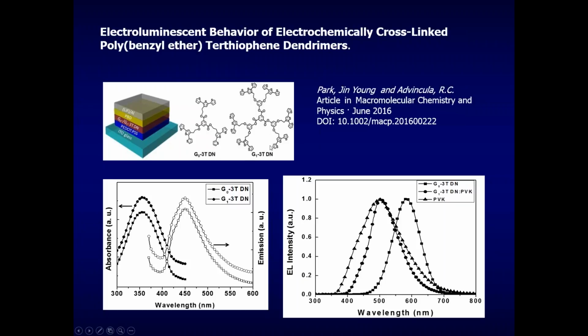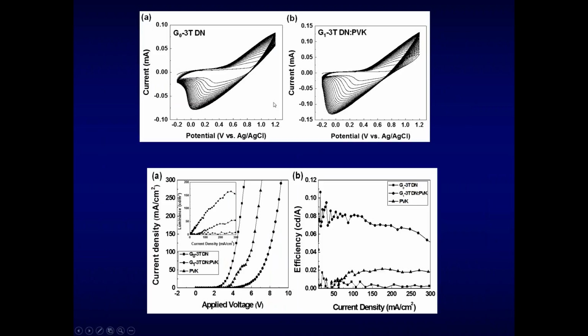Now, we have investigated actually the use of different types of thiophene cores for electroluminescent display devices. In this case, we have these 2 dendrimers with thiophene groups, again showing their absorption and fluorescence behavior. The fluorescence for the thiophene indicates a fluorescence of around 450. And then we can actually complex this as well as copolymerize with PVK to observe a shift in electroluminescence from 550 to 600. So by electrochemically cross-linking the thiophene units, we end up producing polythiophene units that show this dramatic shift in the fluorescence behavior.